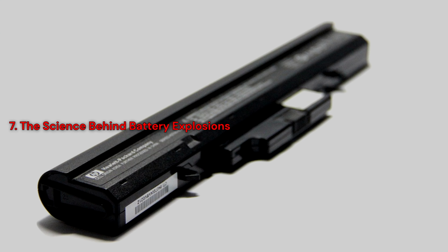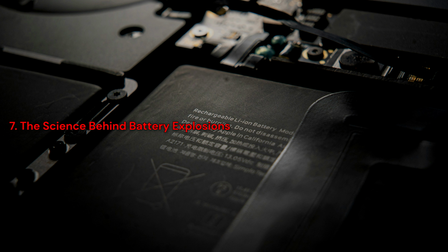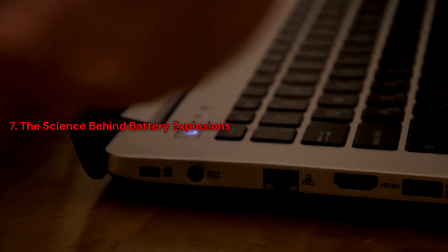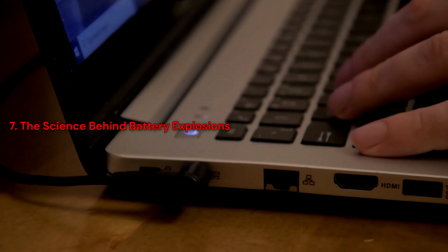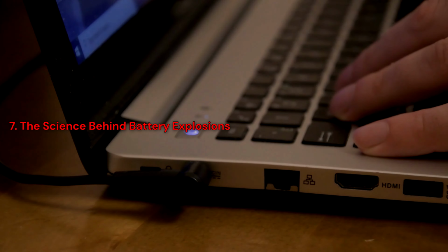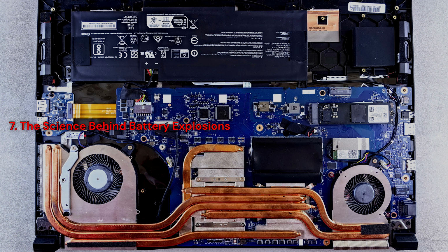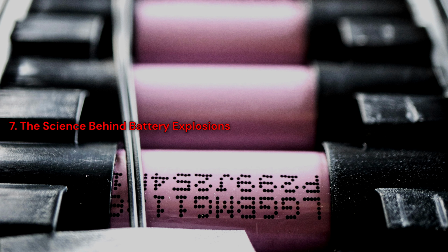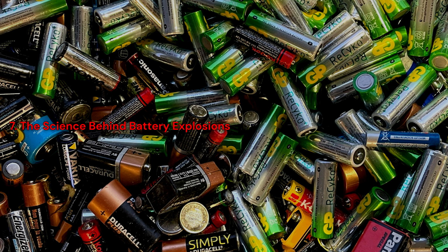Let's address something serious: battery explosions. While rare, they can happen, and the root cause is often thermal runaway. This occurs when the battery overheats, causing a chain reaction that leads to the breakdown of electrolyte and the release of flammable gases. If the battery's internal pressure gets too high, it can rupture and ignite. One technical reason for this is internal short circuits. These can happen due to manufacturing defects, physical damage, or the growth of dendrites, tiny, needle-like structures that form on the electrodes over time. Dendrites can pierce the separator between the anode and cathode, causing a short circuit and rapid heating.